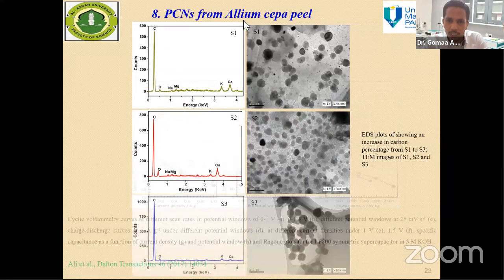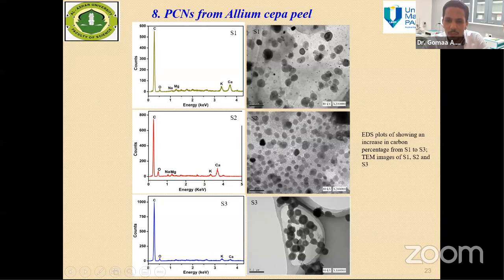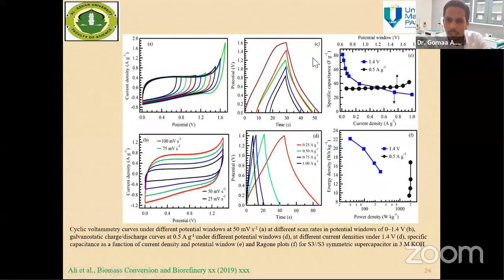Also, we have prepared porous carbon nanosphere from another waste source, and we successfully got the spherical particles of carbon materials, and same investigated for supercapacitor applications at different potential windows, and here this time it is a low specific capacitance around 80, maybe this one is not pure carbon material obtained, so it shows around 80 farad per gram and 22 watt-hour per kg energy density, and this one is from published material in a Biomass Conversion journal.